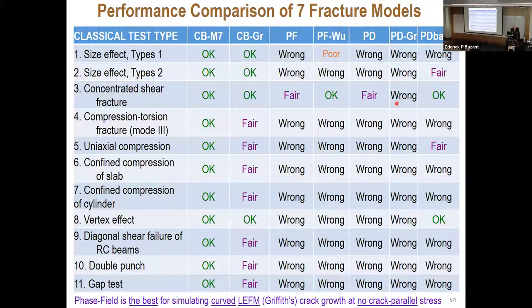But I would like to make a comment on phase field model. I think the basic idea is very interesting, it's clever. Francfort, Marigo and other extensions. And you must admit that it is the best model, phase field, I didn't show it here, for simulating curved LEFM cracks if there is no crack parallel stress. Unfortunately, there are not many situations with no crack parallel stress. That's a rarity.